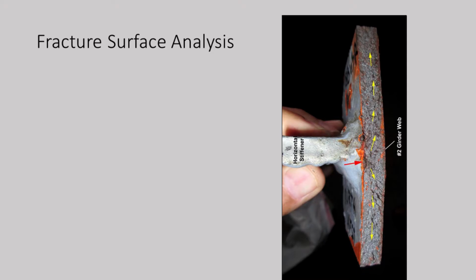And moving forward, what you have here is the portion of the fracture surface. This is the web, and this is that horizontal stiffener. And you can see this gloppy fillet weld that attaches the horizontal stiffener to the web. And if you look at this fracture surface, it's pretty grainy, typical of a brittle fracture in steel.